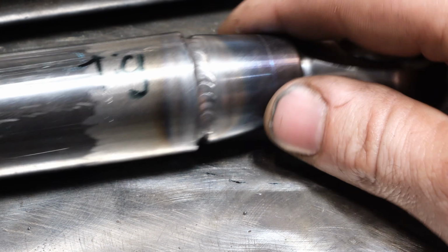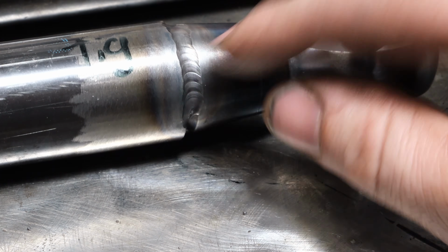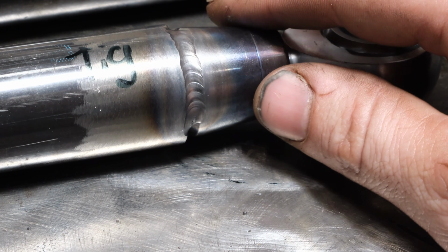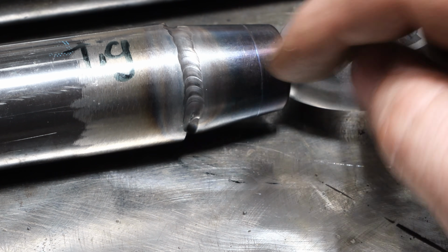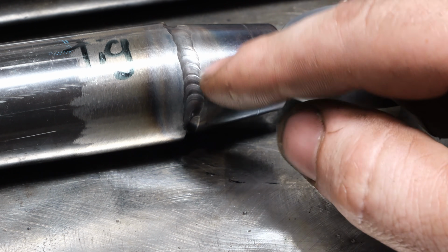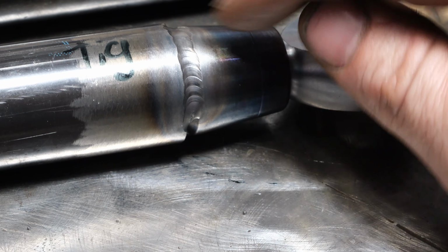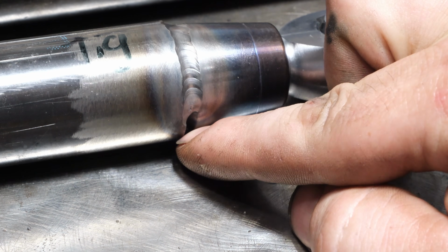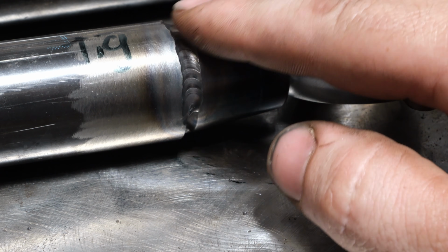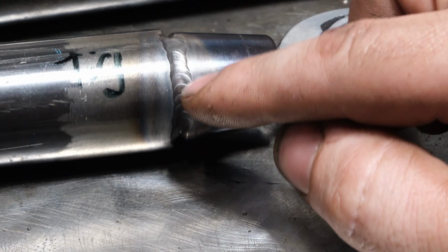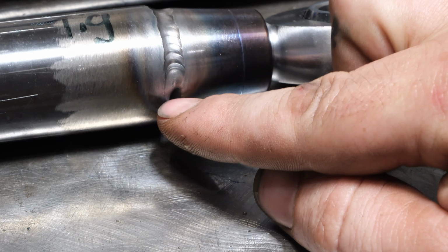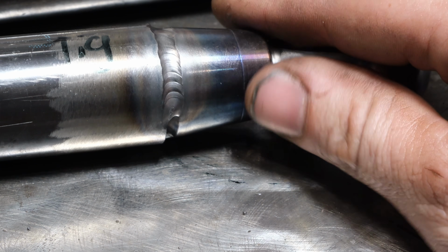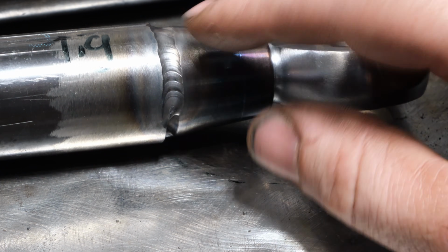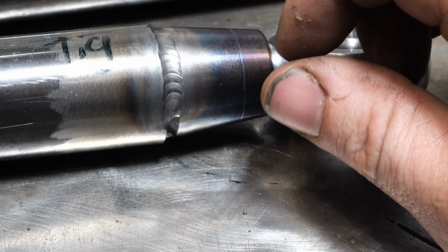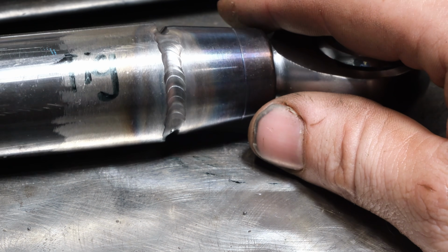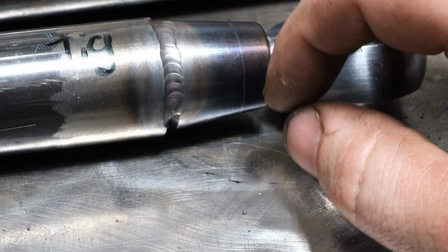This welded okay with TIG. One of the issues you have with that big wide gap that was there is running enough heat to both join both sides and then melt anything down in the root. You're far better off running a very tight arc first pass and then going back over it to fill it. By running higher amperage, I think it was at 165 on this, and then just trying to do it in one pass, you're going to end up, like I said, with inadequate throat thickness. So the weld thickness is going to be minimal, and the overall strength of this probably is not going to be that good. So don't do that.